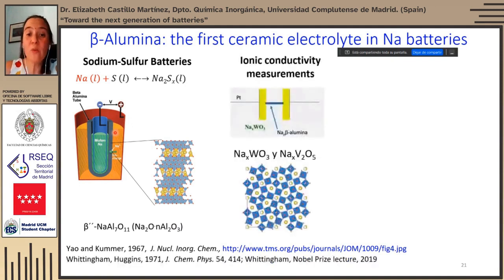Actually, it was in order to study the ionic conductivity of this beta alumina that Professor Whittingham took some insertion electrodes, which could have variable amounts of sodium in their cavities, to do this measurement, and somehow started insertion chemistry. Beta alumina was also used at room temperature by Professor Michel Armand in a sodium battery with a graphite intercalation electrode.